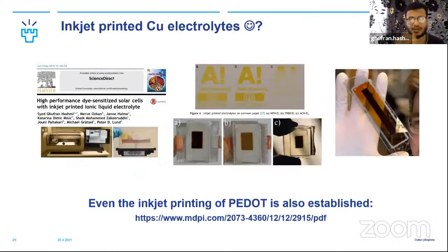Similarly, not only the dye, we also showed that even the electrolyte can be successfully printed. This was one of the reports, with an ionic liquid based electrolyte with an iodide triiodide redox shuttle, that was successfully printed over the titania layer. And what does it allow? It allows us to produce hole-free solar cells.